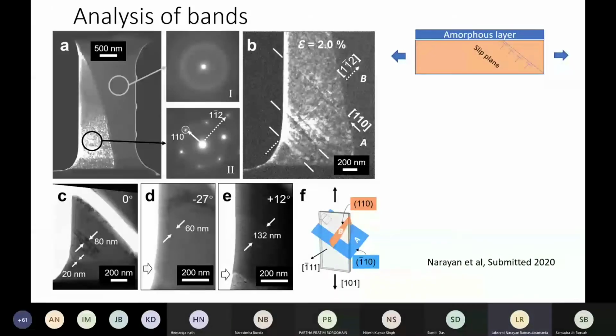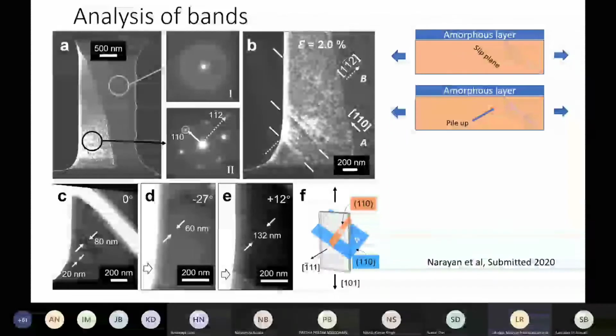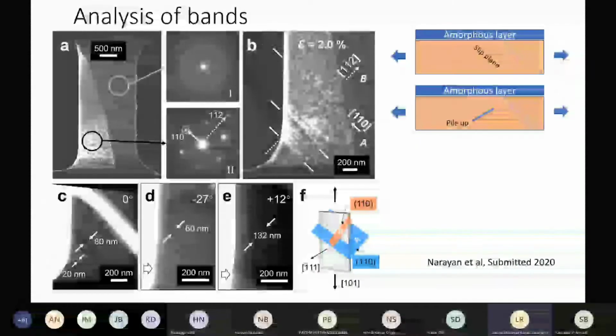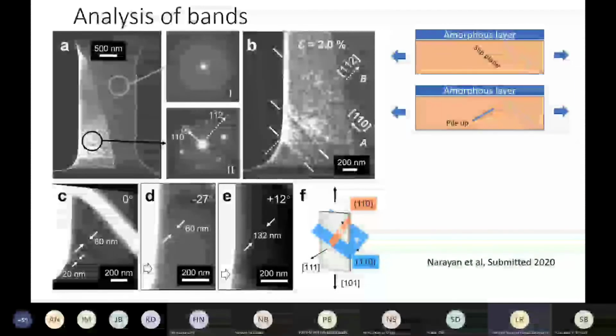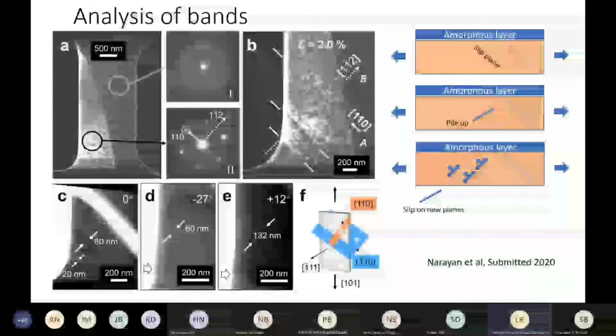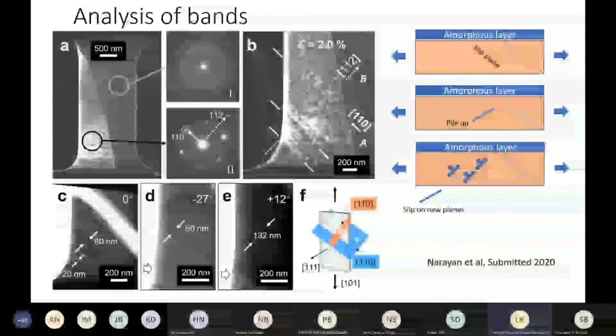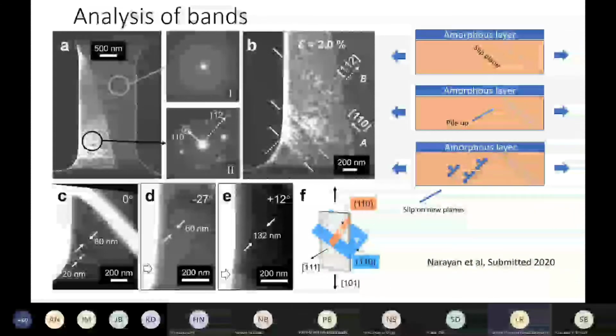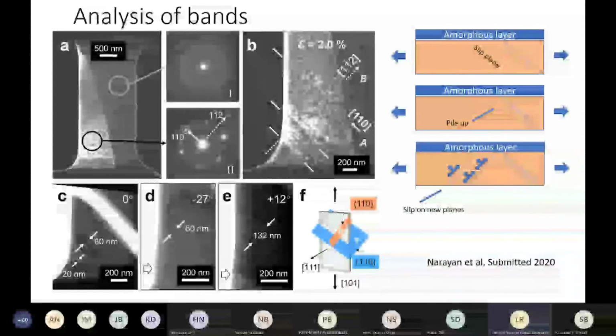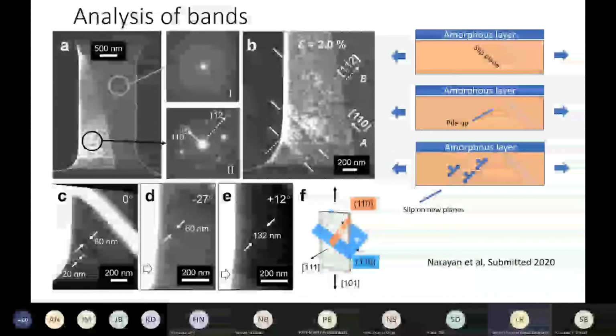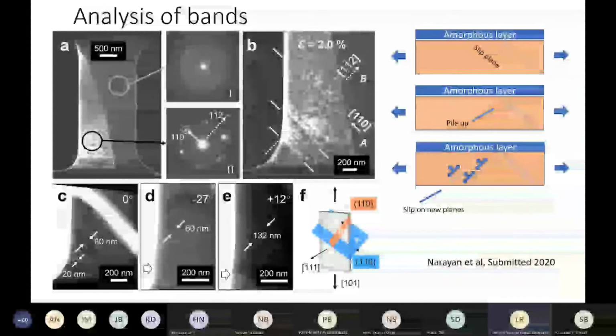So the amorphous layer is essentially blocking this particular slip, and this will lead to a pileup, which means that dislocations will interact more, but since they cannot go further, this particular plane will become strain hardened. And then you will now activate another slip plane in some other part of the crystal, which is what was happening. As you saw as a thick dark band, dislocations were getting activated on another part of the crystal, and these dislocations start moving towards the amorphous layer, and again they get trapped. In fact, they get blocked, and they do not allow further dislocations to develop along this plane, which strain hardens the crystal further. Now, if several of these events occur all over the crystal, it leads to homogeneous deformation, or distribution of strain in the crystal, because of activation of slip on different areas of the crystal.